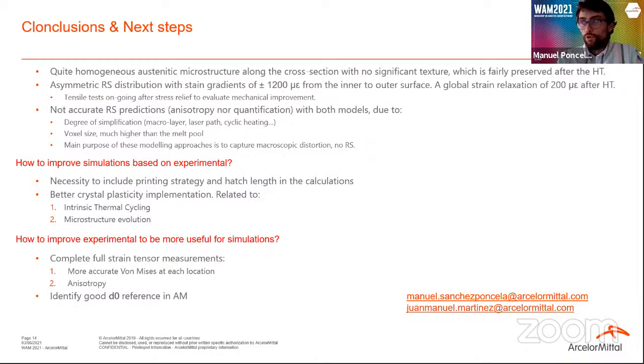But what they do not do right now is to predict the residual stresses. So to better capture this stress distribution, it is needed to implement the scan strategy. This is key, and also to have a better crystal plasticity implementation of the material, to account for the intrinsic heat treatment of the material from the upper layers when they are printed.